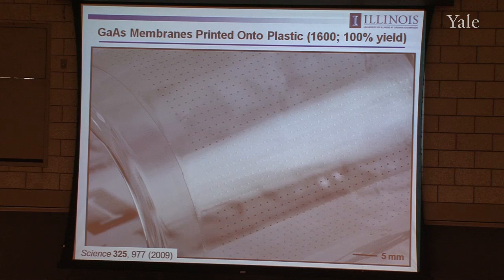So this is what it looks like if you run that tool, use that kind of concept, create these nanomembranes in the ways that I showed you before. In this case, it's an array of gallium arsenide nanomembranes created in a densely packed configuration on the source wafer and then spread out at low areal coverage in a step-and-repeat printing mode onto a sheet of plastic, which is what you see here, which is subsequently wrapped around a cylindrical glass support. Each one of these nanomembranes is about 250 microns on the side, about the size of a human hair roughly, 200 nanometers thick, and printed in this case is about 1,600 of them with 100% yield. So it's really demonstrating very high levels of control, both in the process as well as in the control of the adhesion for the assembly.